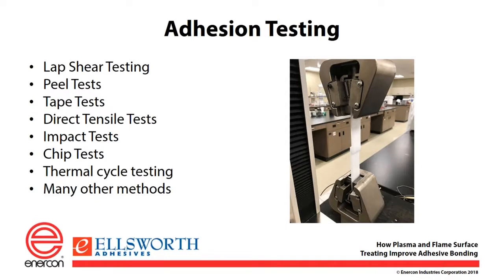There are many different tape tests where you have a material on a substrate and you typically will crosshatch it. There are tools that are designed for creating very even crosshatch patterns. Alternatively, many people will just use a razor blade and cut into it, or they might cut an X into it. And then you apply the tape over the surface and you rip the tape off to see whether or not the material is removed from your substrate. There are many different types of tapes with varying strengths, so it's important to make sure that you're consistent in how you do your tape tests.